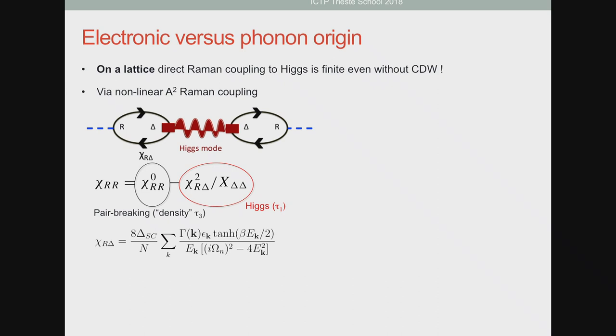And then I can show that my Raman response will involve a first term here, which I label chi 0. This is the regular pair breaking term. So this is the one that is giving me a sharp peak at 2 delta and the continuum. And if I insert the Higgs mode here, I will have an additional term. So if you want, this term will be in the density channel, so tau 3 in terms of Pauli matrices, and this one will be in the pairing channel, tau 1. And what you can see is that here in the numerator, this has this form.